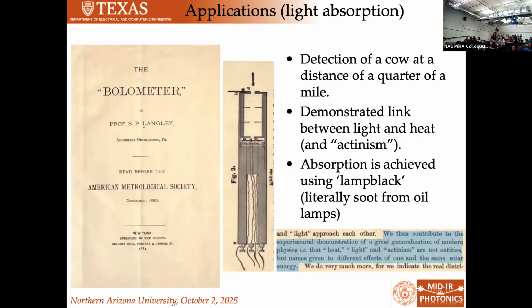But that's not to say that there aren't applications. In fact, you can go back to 1881. So again, cutting edge science here today, to the introduction of this thing called bolometers, the first infrared detector. Basically, it's a Wheatstone bridge with an IR absorbing material, lampblack soot, on one of the arms, right? And essentially, when light hits that, it heats it up, it changes the balance of your bridge. And this could actually detect the thermal emission from a cow at a quarter of a mile in 1881, right? This is actually really impressive.